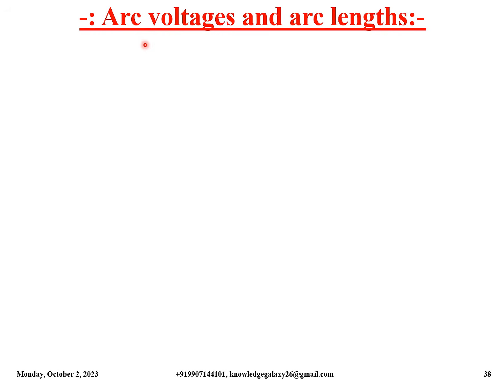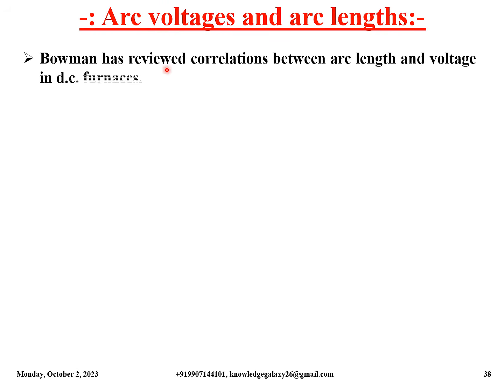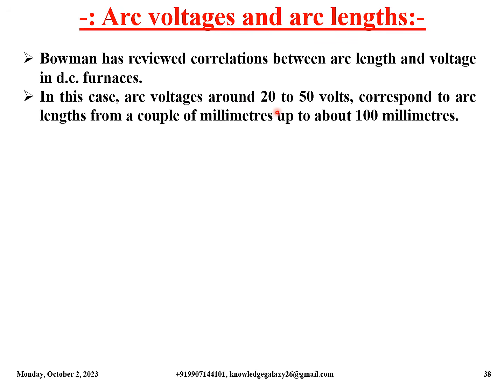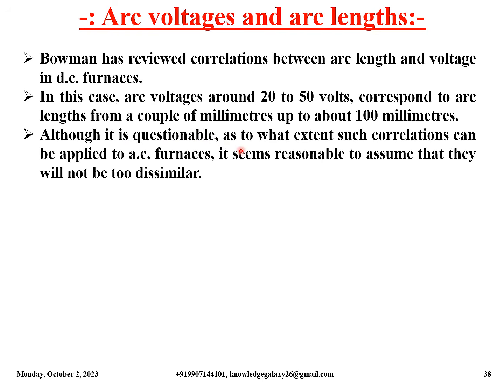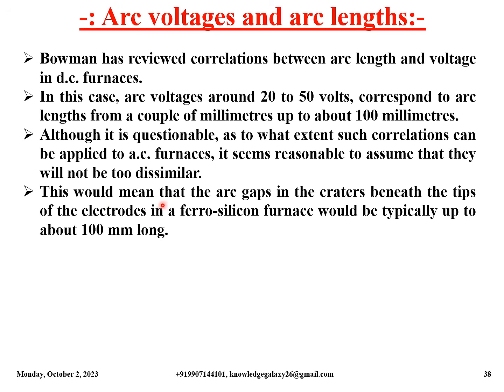Now let us have some discussion about arc voltages and arc lengths. Bowman has reviewed correlations between arc lengths and arc voltages in DC furnaces. In this case, the arc voltages around 20 to 50 volts correspond to arc lengths from a couple of millimeters up to about 100 millimeters. Although it is questionable as to what extent such correlations can be applied to AC furnaces, it seems reasonable to assume that they will not be too dissimilar. This would mean that the arc gaps in the craters beneath the tips of the electrodes in a ferrosilicon furnace would be typically up to about 100 millimeters long.